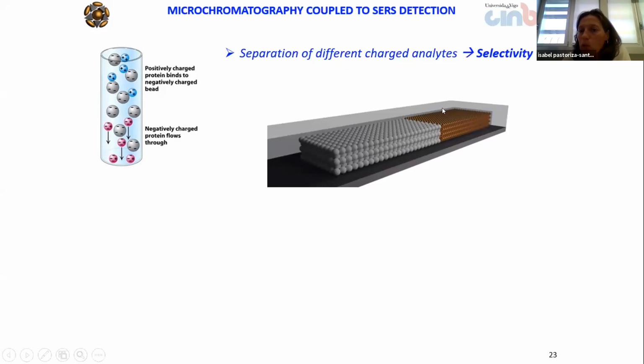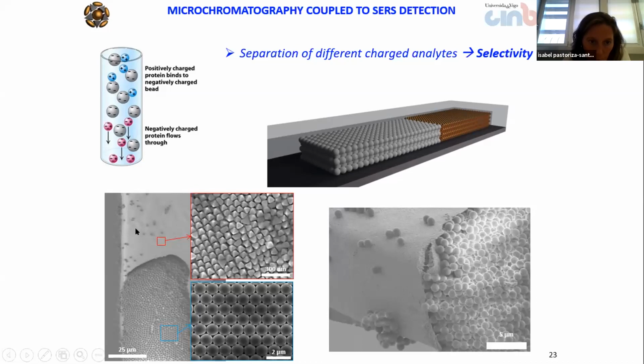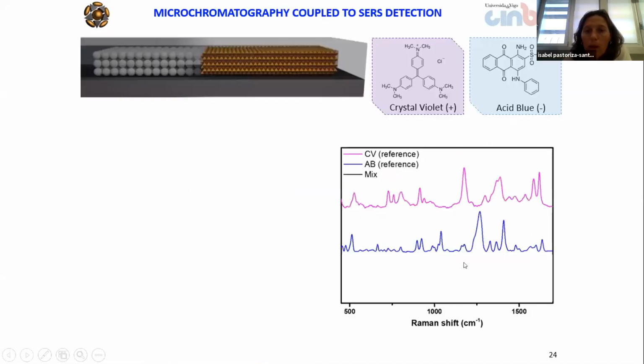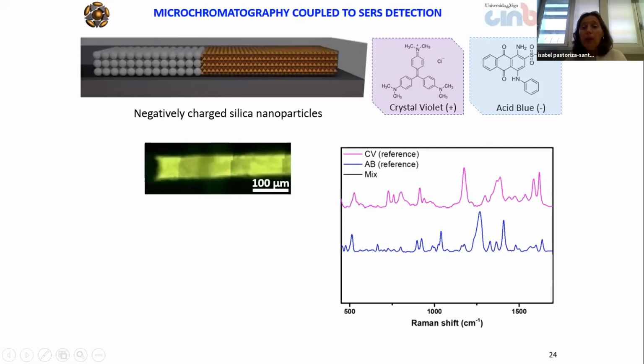Therefore, in our microfluidic channel, we also integrated silica particles after the plasmonic supercrystal. This is the characterization: this is the channel, this is the plasmonic supercrystal, this is the silica nanoparticles, which are self-assembled, and this is a cross section where we can see the interface between both types of assemblies. So in order now to prove the selectivity, we have selected again the same molecules: crystal violet that presents positive functional groups, and the acid blue that presents negative functional groups.